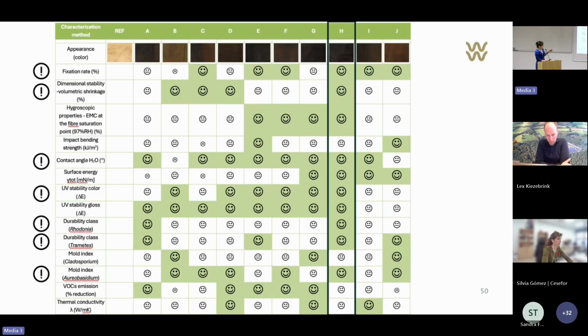After that, we were able to identify our superhero treatment. That was treatment H, which performed best in the most critical aspects. For example, we were considering the color, but also the fixation rate, meaning how much liquid is staying after the leaching was very important. Also the durability was very relevant for us, the shrinkage, swelling, and so on.